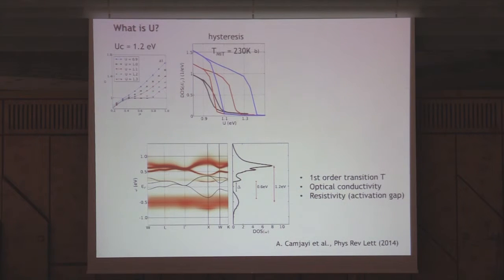And with that, we said, well, can we predict, put a number on what is the hysteresis that this system should have? So this is done here. So this is for different temperatures. These are the coexistence of solutions that you get on this range of values. So U 1.2 would be over there. So you see that there are hysteresis regimes at low temperature. And as you go to high temperature, the hysteresis becomes very small. So the black curve is 230 Kelvin, and above that, the hysteresis just becomes experimentally irrelevant. So this is our prediction to the coexistence regime.